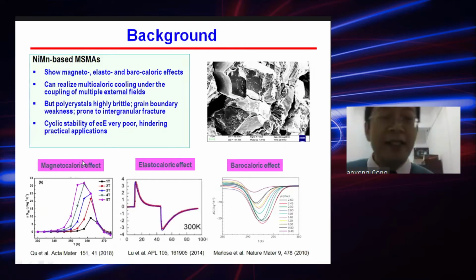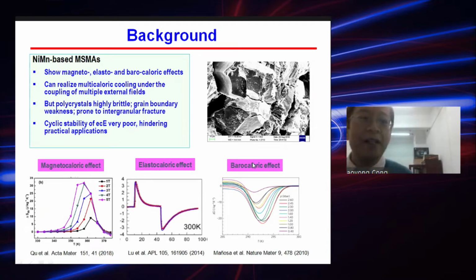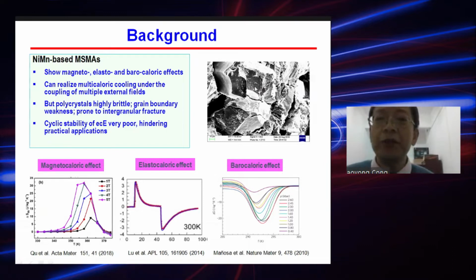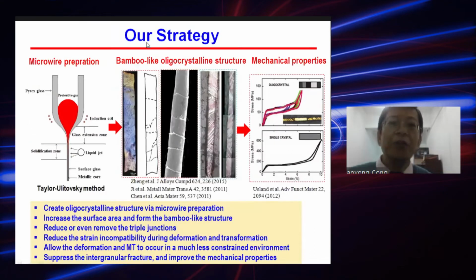We know that nickel-manganese-based magnetic shape memory alloys show multifunctional properties, including magnetocaloric effect, elastocaloric effect, and barocaloric effect. And it can realize multicaloric cooling under the coupling of multiple external fields. But the polycrystals are very brittle, the grain boundaries are very weak, and they are prone to intergranular fracture during loading. Therefore, the cyclic stability of the elastocaloric effect is very poor, which hinders its practical applications. Our strategy is to create this kind of oligocrystalline structure through microwire preparation. With this kind of structure, we can increase the surface area and form a bamboo-like structure.